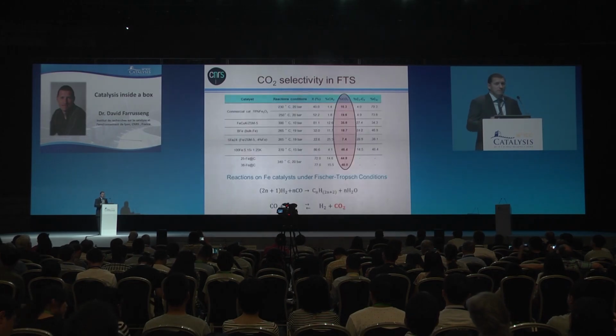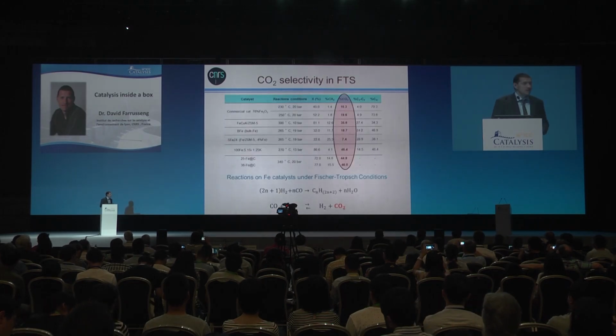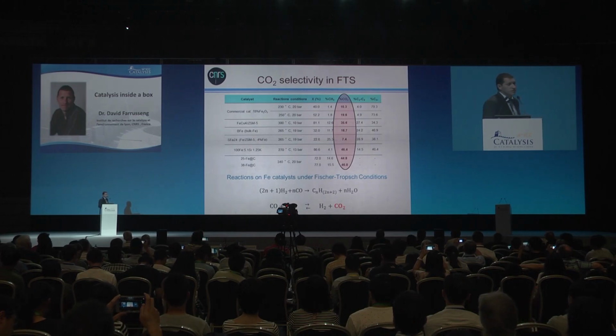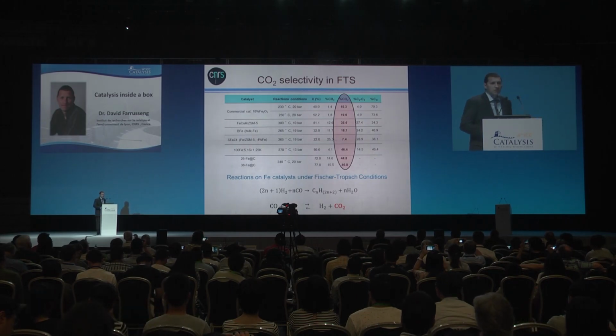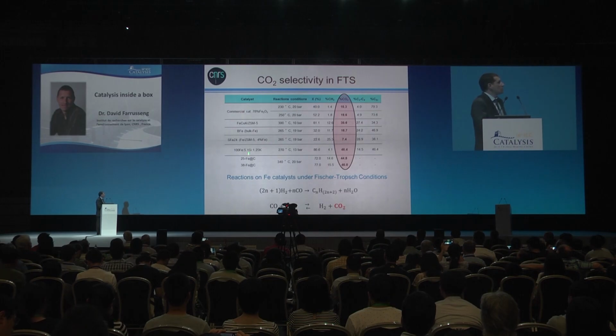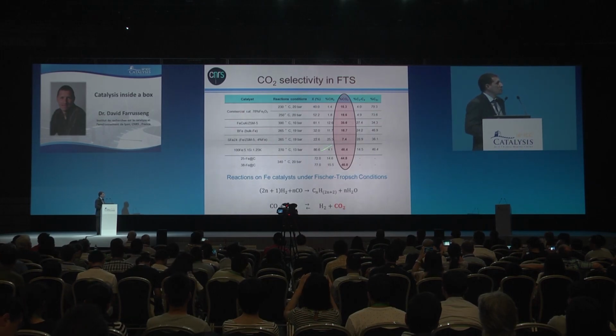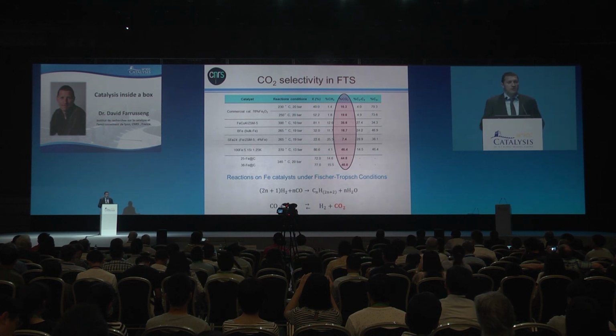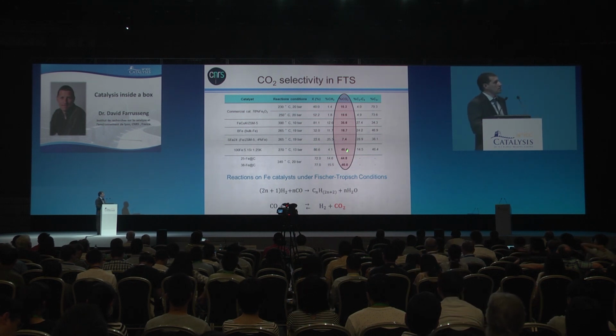But back to the selectivity, right? Here is the list of different catalysts we found in the literature, all based on iron, and you can see that whatever the composition, whatever the operating conditions, they all produce CO2.